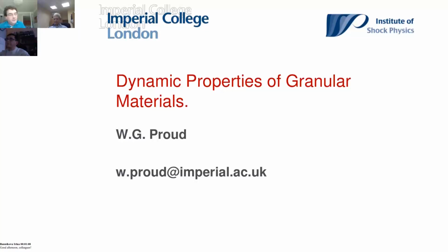Now, the one thing I didn't mention in the talk is the things called rattlers. So a rattler is where you've got these big particles, and in the bottom of that void between those big particles, you've got a small particle. That small particle sits inside that void, and it's called a rattler because if you shook it, then it would bounce around and make a rattling noise. The thing is, as you compact that polydispersed material, those big particles, for sure, they change their degree of contact. But all of a sudden, you get to the point where that small particle now starts to interact, and the number of points of contact has changed during the compaction.